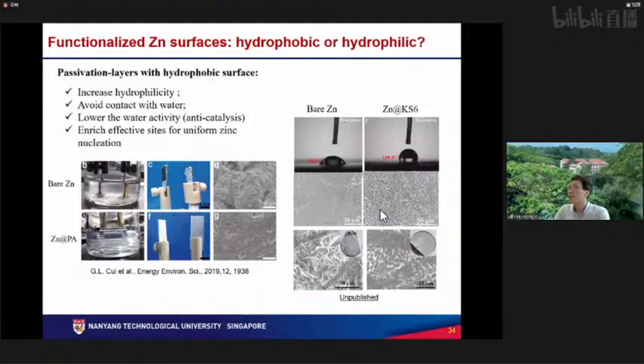We coated the surface with KS6, some material, and made the surface actually hydrophobic. Okay? This makes the surface less wettable. But we also find that we have a similar effect. The surface has fewer spikes and the dendrites are less severe compared to bare zinc. So sometimes we find that a surface coating or passivation layer does not simply make the surface wettable by the electrolytes. It may have some other effects, and the overall performance, the dendrite and self-corrosion, is a result of multiple factors.